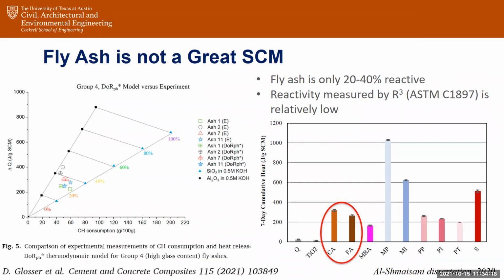All right. When we're looking at finding supplementary cementitious materials, our gold standard is fly ash. But what's great about having fly ash as a gold standard is that it's not actually a great material. It's kind of a mediocre performer. In terms of reactivity, it's only 20 to 40% reactive. And compared to many other materials that we are interested in as supplementary cementitious materials, it's more or less average to low. So when we're talking about a substitute, at least we're not aiming really high. We're aiming for something relatively mediocre, which is good to know.